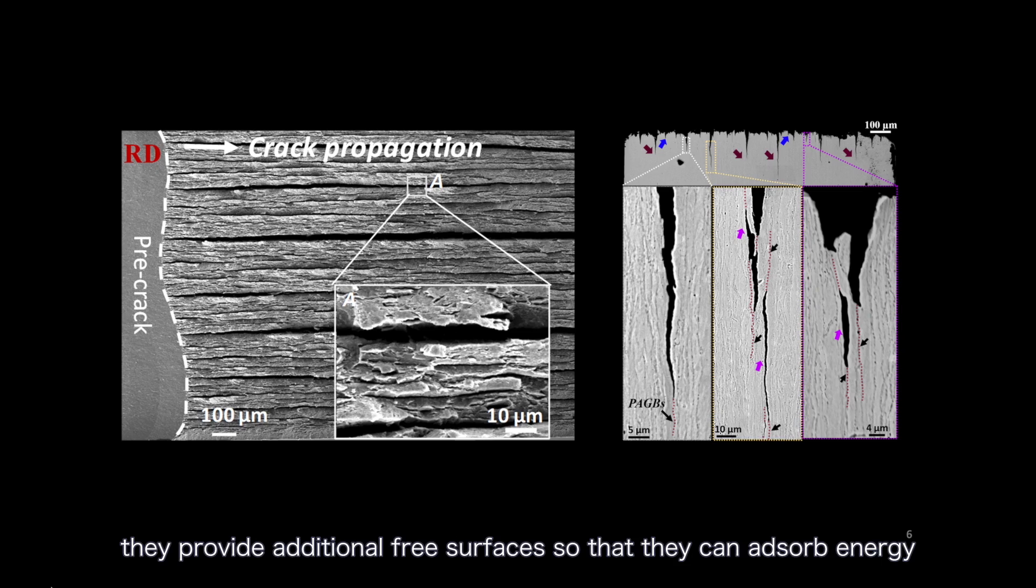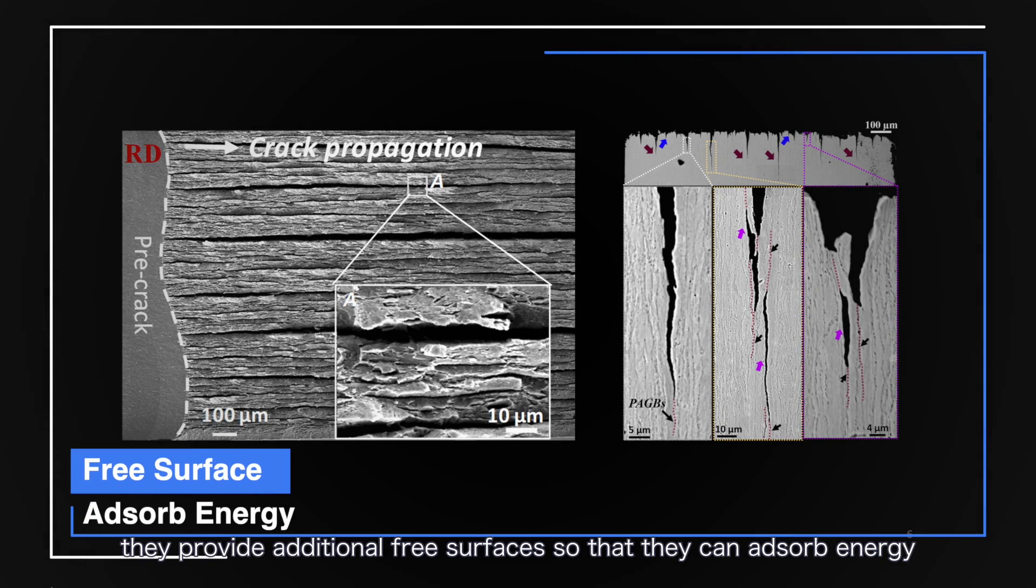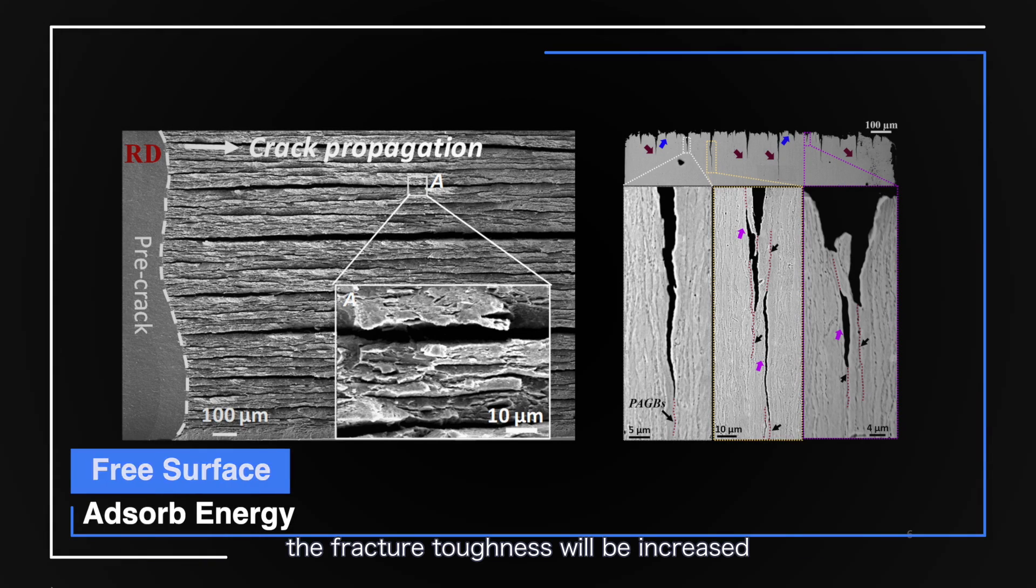In addition, they provide additional free surface so that they can absorb energy. In this way, the fracture toughness will be increased.